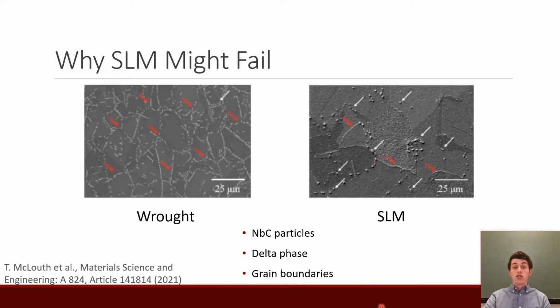Another important distinction seen is the formation of the delta phase. In selective laser melting, this forms along the grain boundary, whereas in wrought samples, it's seen forming radiating from the interior of grains outward across grain boundaries. This can be seen in these images as the red lines. Here on the selective laser melted sample, we see these thin lines of delta phase particles forming smoothly along grain boundaries. However, moving over to the wrought sample, we see no such constraints and they break several grain boundary lines.